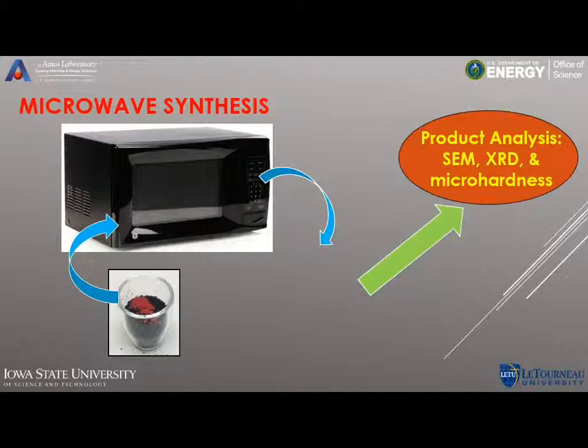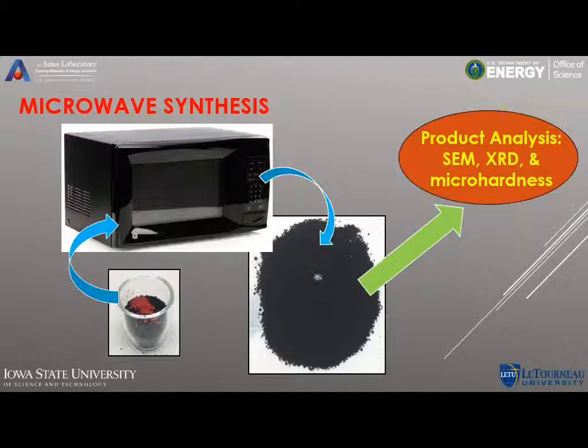0.5 to 2 minutes. And in that time period, you would often get plasma forming that you would see, and then a fair amount of noise associated with that. But at the end, we would get this metallic product that formed. Especially with the iron, you could get a nice, clear conglomerate of metal. And then we'd take that and prepare it in various ways to analyze it by scanning electron microscopy, or SEM, X-ray diffraction, or XRD, and then microhardness testing as well.